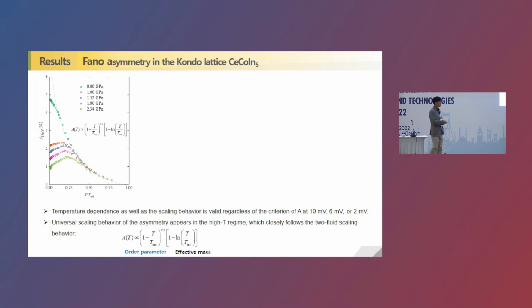Okay, so in order to quantify the Fano asymmetry, we used the so-called 10 millivolt criterion. What we did is compare the minus 10 millivolt value and plus 10 millivolt value, and then took the ratio. The x-axis is the temperature normalized by the so-called saturation temperature, where you do not see this asymmetry. You can see that at different pressures, in the high temperature region, they scale pretty well together.